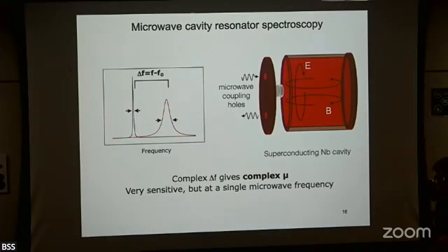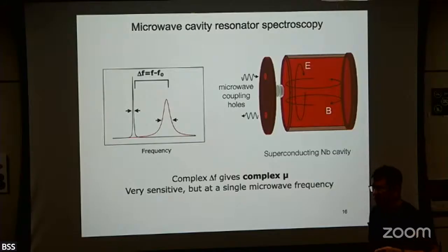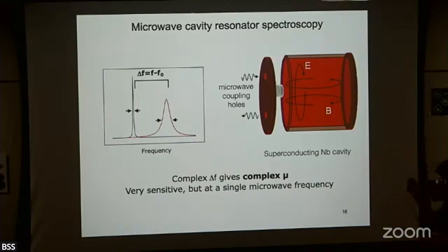Just to be sure, what's inside the box is a cavity that's a vacuum, and then also a piece of niobium? Yeah. First there's nothing in there, just an empty box, and then I take the cavity apart. We do it a little bit more sophisticated, but you could imagine this: you place the sample inside, put the box back together, and measure again. Then I need to solve some electrodynamics problem about what the response of this cavity would be with a bit of niobium, with a bit of something inside it with a different dielectric constant.